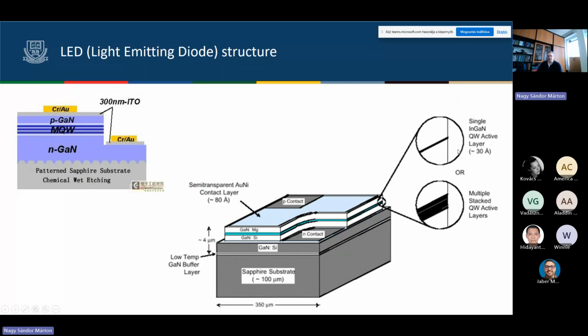Okay, our next topic will be the LED, light emitting diode, and its structure. It's a good example of a very small piece with very thin layers on each other. With gallium nitride and indium nitride, it is very hard to remove these layers. But there we also can see some gold wires. You will see here later on the optical microscopy. As you can see, the thickness of this layer is approximately 4 micrometer, and the LED chip, what you can see here, is 100 micrometers. So it's really thin layers that can be seen here.